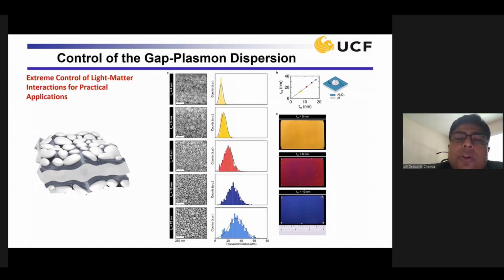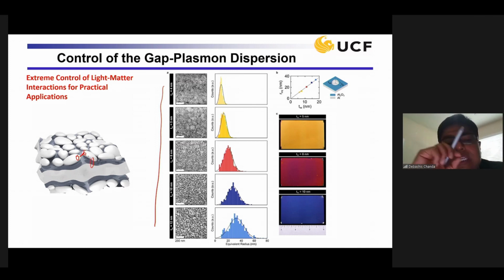We're just changing the nanoparticle dimension of simply aluminum. There's nothing else in it. It's simply an oxide and aluminum combination of engineered dimension to get the plasmon resonance right. There are two resonances. One is this gap plasmon resonance between the gap, and there is also a vertical resonance. This is basically a small narrow cavity. You couple this gap plasmon with a cavity. This is a thick mirror. It forms a cavity. You couple them, and that's the reason you get this vibrant color. You can produce that just by changing dimension. You can actually change the color swatch.